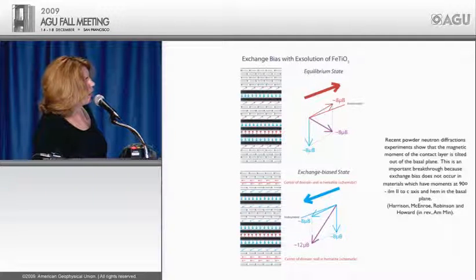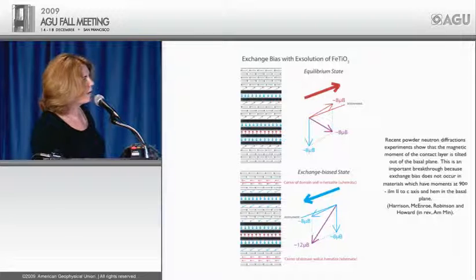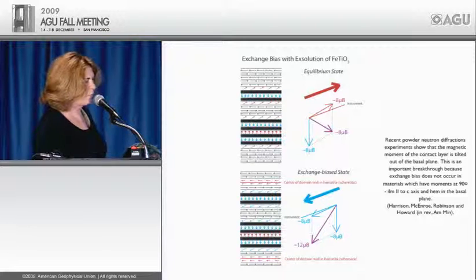So here is just a sketch of the exchange bias state. These results are coming from a neutron powder experiment we ran last winter, and this is now in review. What we found in the neutron experiment is that the hematite is rotated out of the plane. And it's not only rotated out of the plane at very low temperature; in these materials with very nanoscale lamellae, we're seeing it's rotated out of the basal plane even at room temperature.